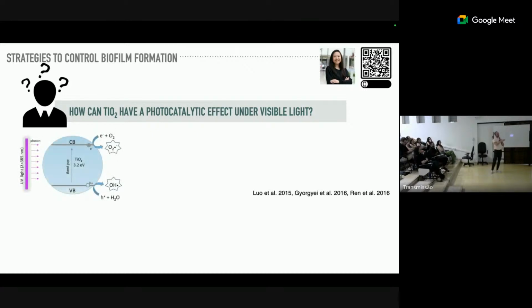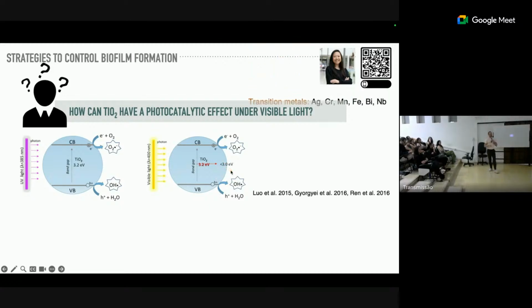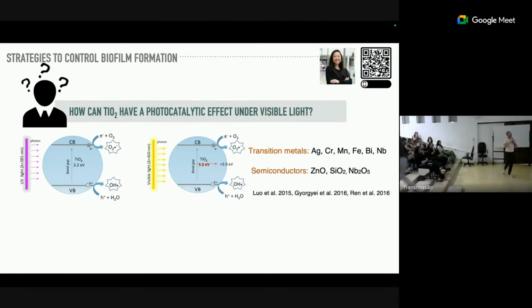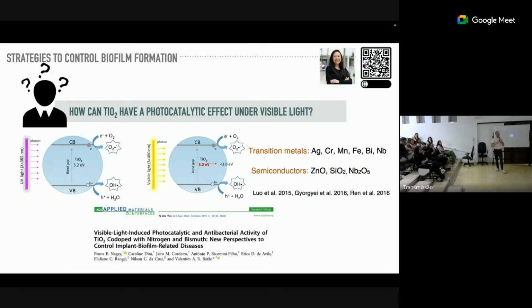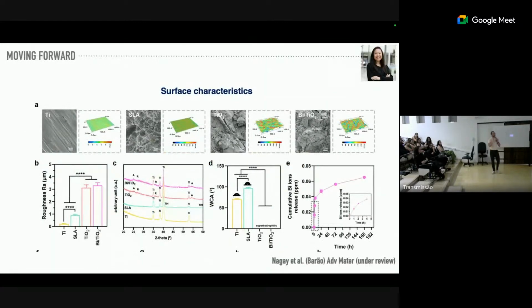As I mentioned, we need to reduce this band gap here, that is normally 3.2 electron volts, so it is stimulated by the UV light. But to have a stimulation under visible light, you need to have a band gap lower than 3.0 electron volts. You might find in the literature several strategies to provide this effect under visible light using transition metals or using semiconductors. So this is the first study that we published using this photocatalytic effect under visible light.